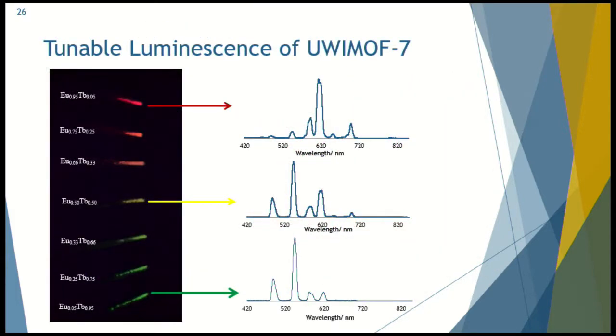So the europium and terbium analogs of these compounds emit strong red and green light. However, if we made these materials with a mixture of both europium and terbium metals, we were able to control the emission color from red to orange to yellow-green to green, depending on the relative ratios of these metals. Our photoluminescence spectra showed that they had both europium 5D0 to 7FJ transitions, as well as terbium 5D4 to 7FJ transitions. But of course, the relative intensities vary depending on the concentration, and was consistent with the emission color that we see. So, of course, we're continuing to do studies on these materials, especially in sensing.